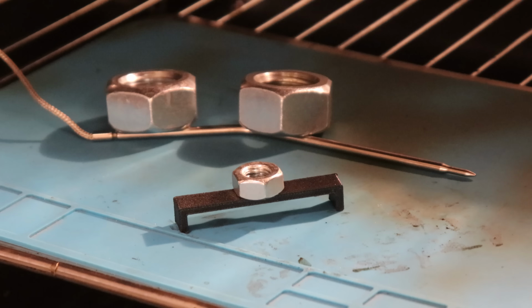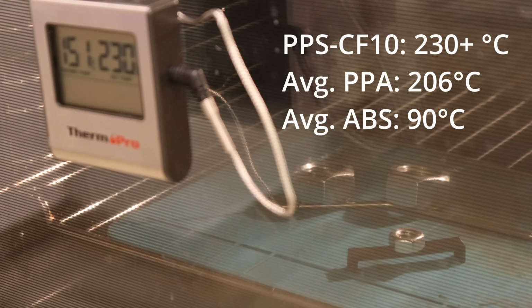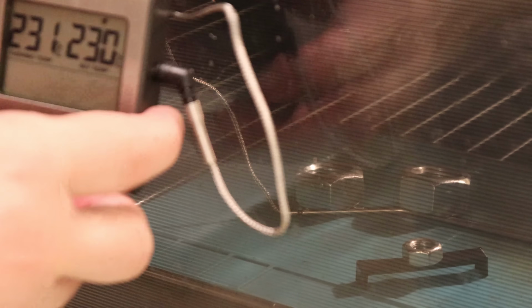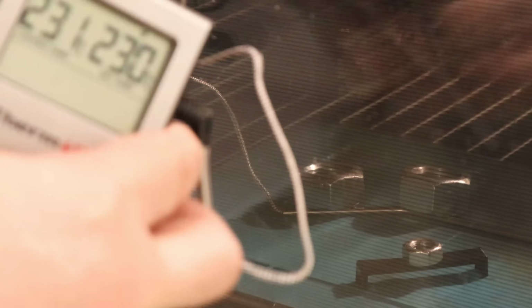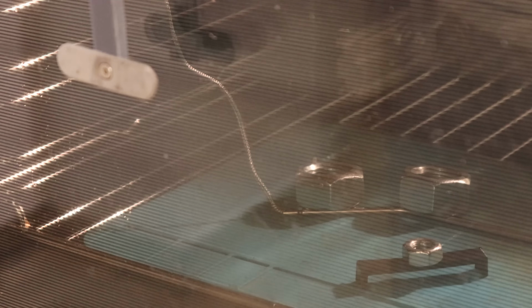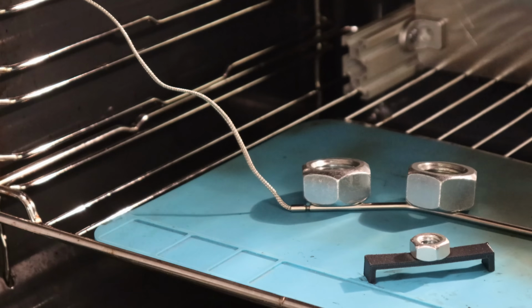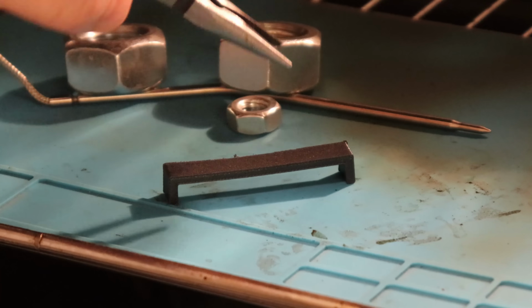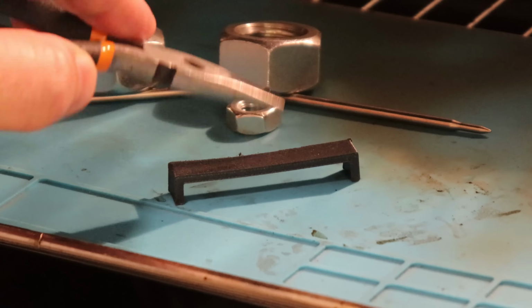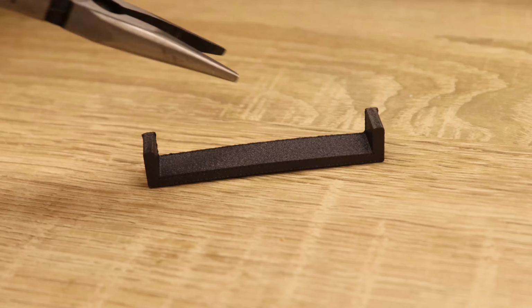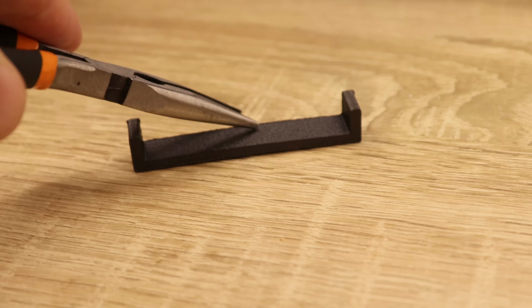The temperature test in the oven. Even from the specifications, I knew that I will reach the maximal temperature of my equipment, and probably I will not record any deformation on this PPS material. Stop the experiment at 230 degrees Celsius. Actually, there's a micro deformation on this test object, but not big enough to record the temperature when it started.